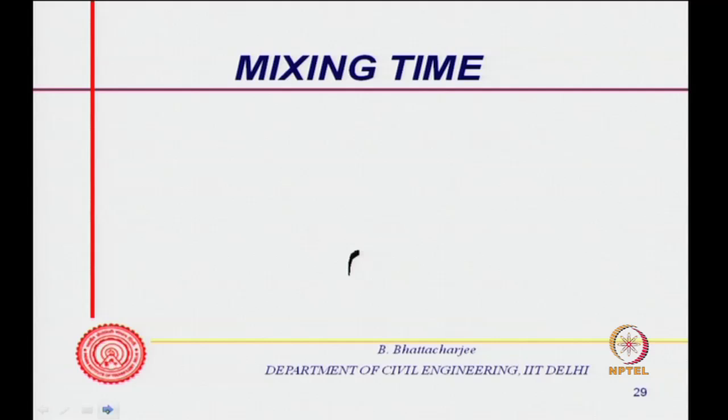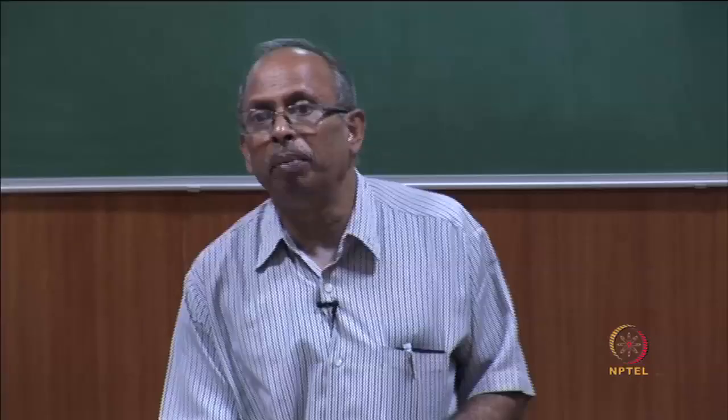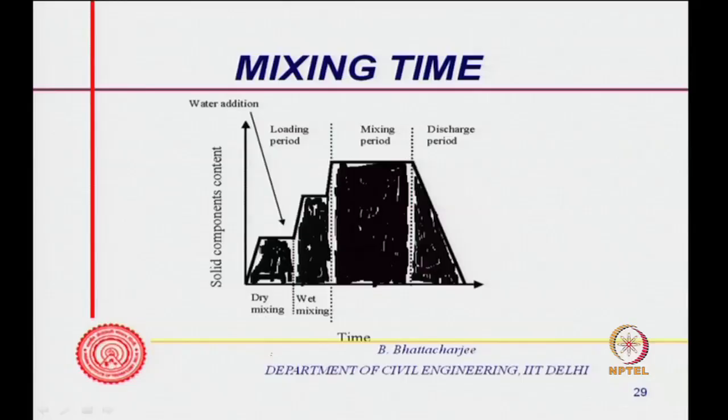Typically, if you look at feeding, the first stage is dry mixing. This is time versus solid component in the mixer machine. First, I just feed in, and during this period I am doing a little bit of dry mixing. Then again I am loading, but in this case some water I have loaded, and this is somewhat wet mixing. Then I load the final quantity of water and it is total mixing. So, this is your true mixing period, and then this is the discharge period.